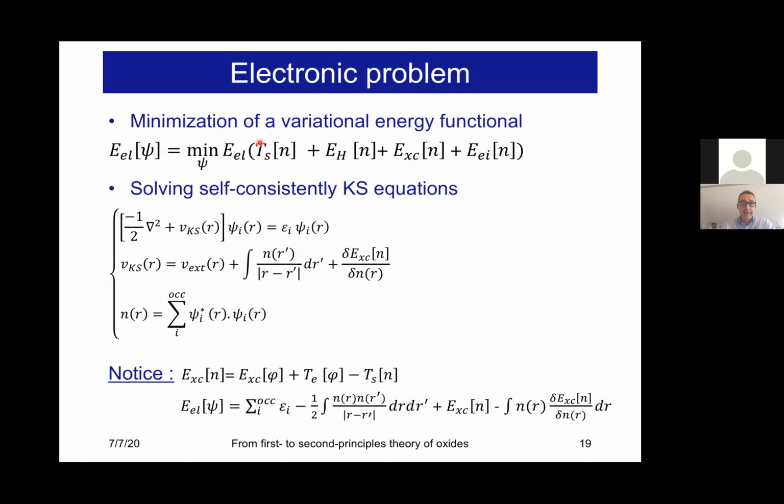You just need to take the derivative of this expression with respect to psi, and you will end up with this kind of equation here, where you see that minimizing this is basically equivalent to solving a one-body Schrödinger equation in which your fictitious non-interacting particles described by the wave function psi are in an external local potential that I call here the Kohn-Sham potential.